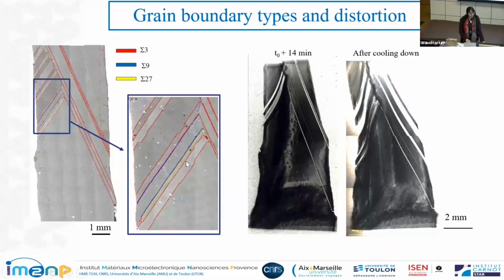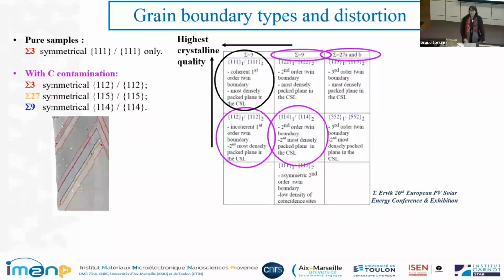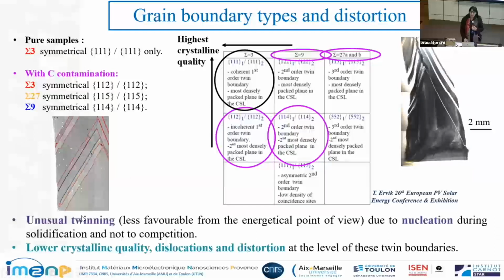So first, coming back to this very particular formation of higher order twin boundaries, what we have during solidification and after cooling down on the topograph is this type of images, which in fact characterizes the bending of the crystallographic planes at the level of these higher order twin boundaries. And this can be related to the lower crystalline quality of this type of twin boundaries that are also incoherent, meaning that you have dislocations inside these twin boundaries. So this unusual twinning, which is less favorable from the energetical point of view, can happen in the presence of carbon, and it is due to nucleation during solidification. And it also goes with the lower crystalline quality, dislocations and distortions at the level of the twin boundaries.